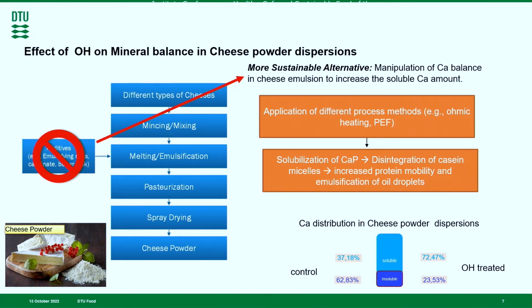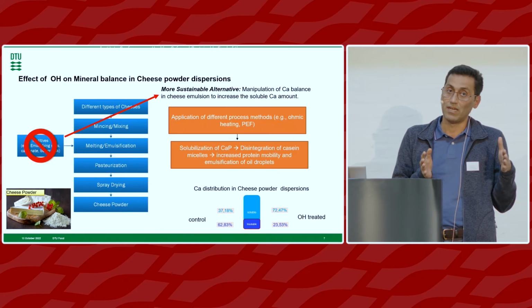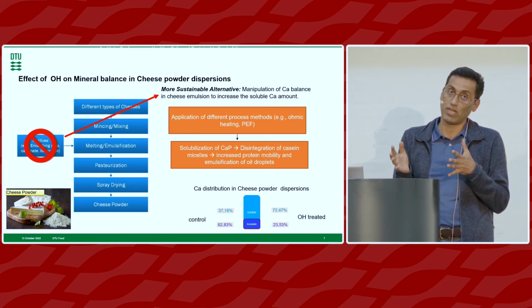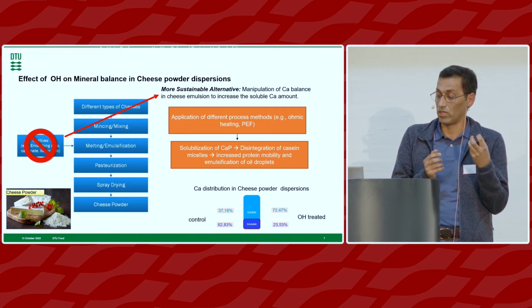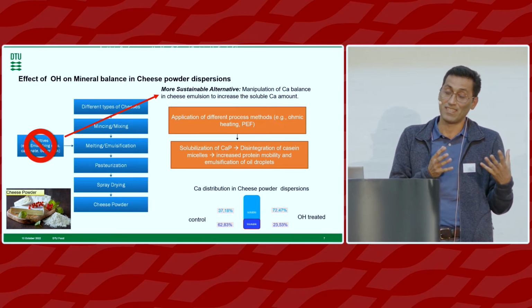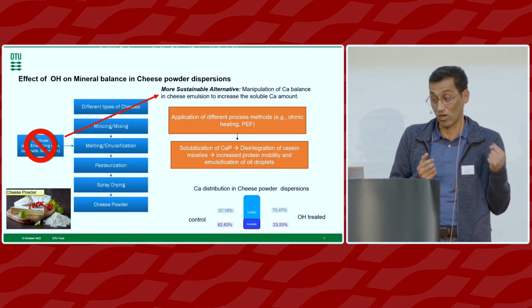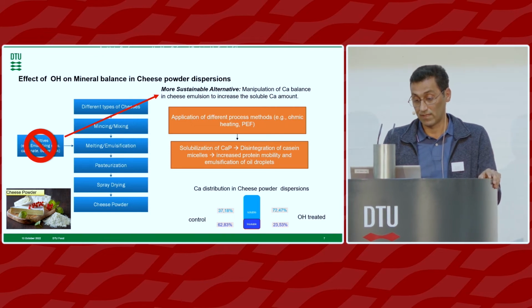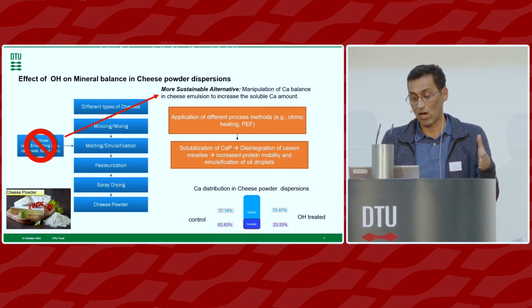And as you can see here, down there on the right-hand side, we have 72% soluble calcium by using ohmic heat treatment, compared to control, which is 37%. And remember, temperature is 85 in both cases. This is important when you want to make cheese powder because you need to have stable emulsions before the spray drying feed, and then you need to have good functionality for protein. And you know that cheese powder is made of cheese melt, which is not soluble. So this is helping us to solve this challenge. Now some companies use additives, melting salt, to solve this problem. So we replace additive with processing.